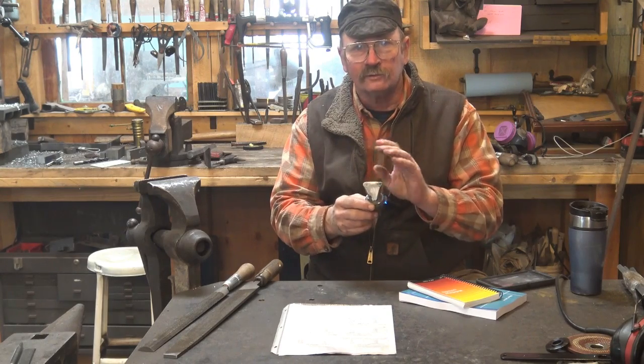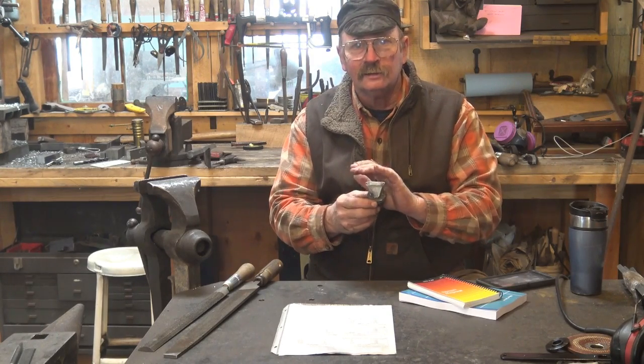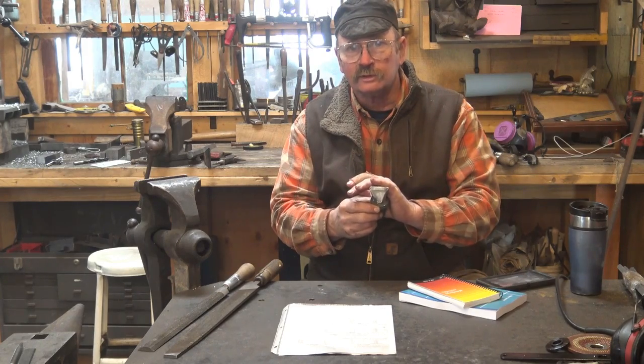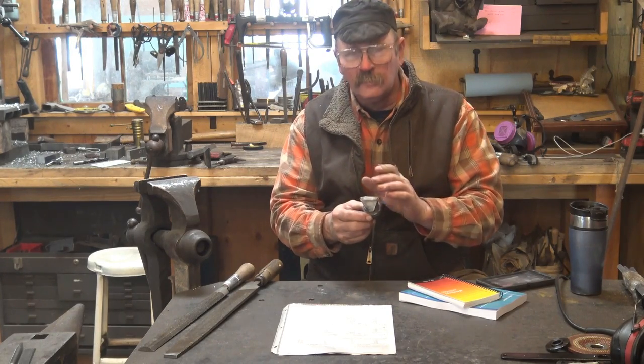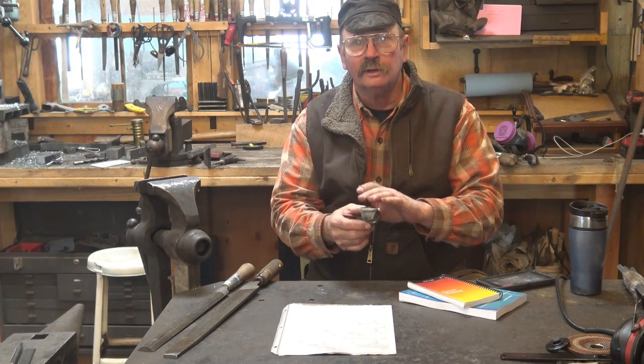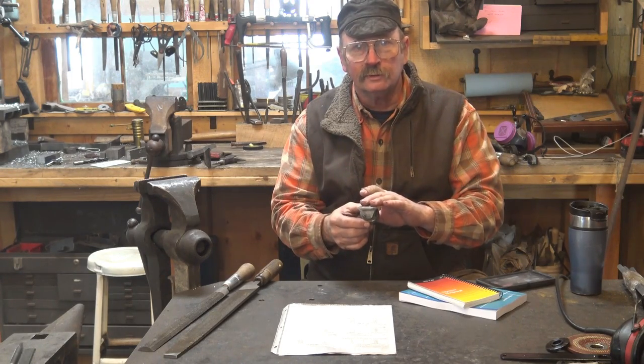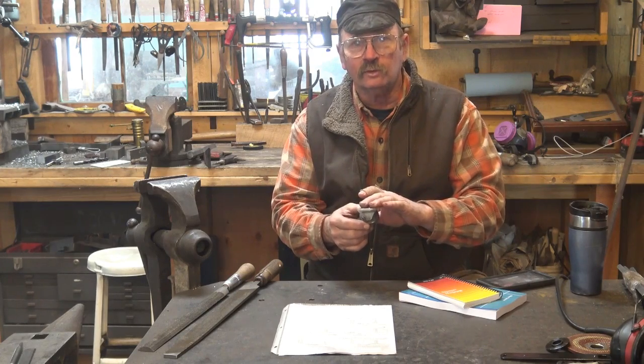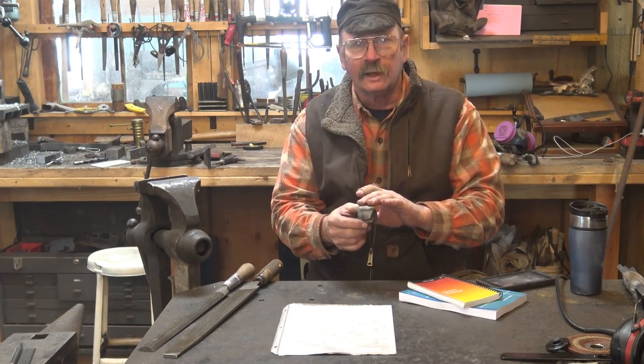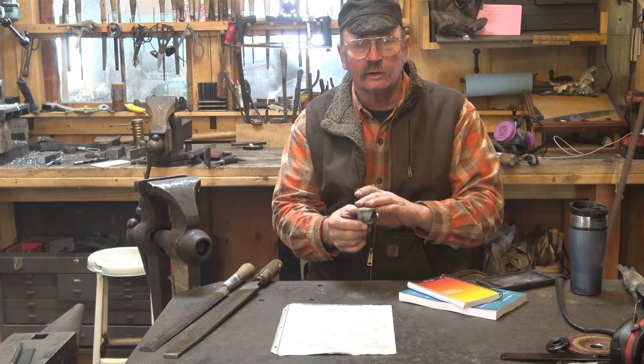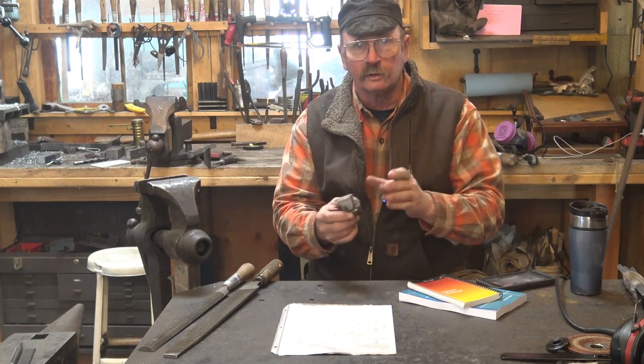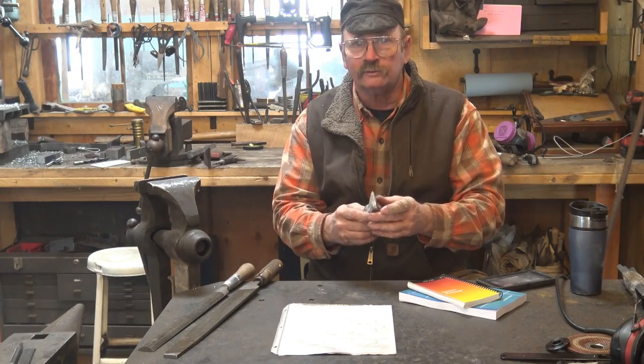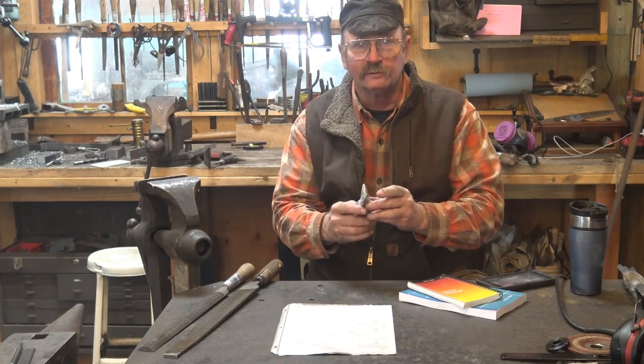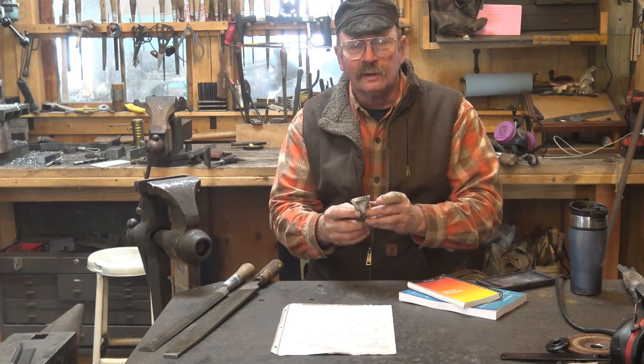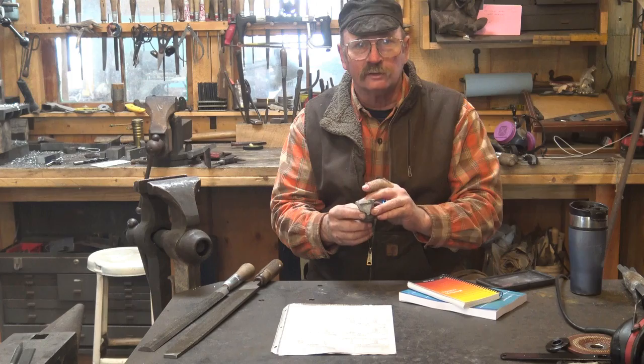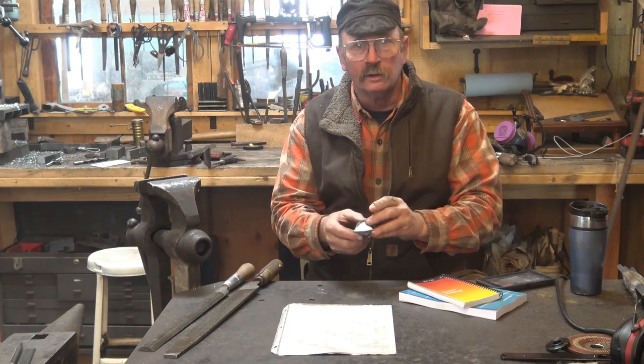Hardening will make this as hard as you can get it. You bring it up to the appropriate temperature, and we'll discuss that in a bit. And then you quench it in the appropriate medium. And different steels have different mediums. Brine is the fastest cooling for tool steels. There's a thing out there called super quench that will actually harden to some degree mild steel, which doesn't harden under any other method. But you don't ever want to use super quench on tool steels. That's a guaranteed way to get a crack. The next fastest quench is water, then oil, and then air.